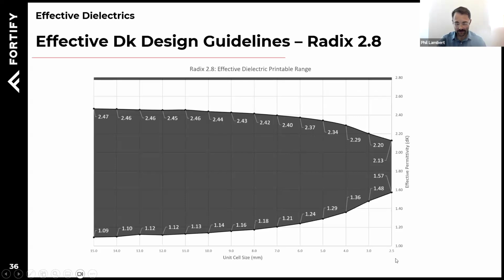And so we would just look real close here, unit cell size based off of my 0.5 lambda guided. We know it's going to be about a 6 millimeter unit cell. And so this is my dielectric range that I can print, these upper and lower bounds are, of course, controlled by the pore size and the minimum wall thickness I can print on the printer using this material. Always, we have the solid material available to us, which is a dielectric constant of 2.8. So there you go. That's your design space that you can use for your application or for your lens.